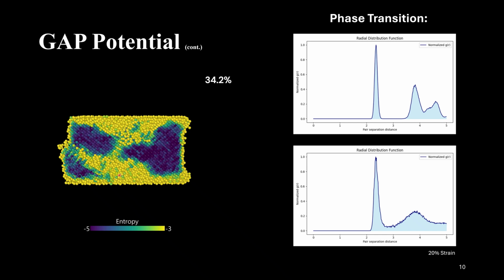And in the experimental paper that I mentioned before and looked deeper into on the next slide, it suggests that the phase transformation for this is a silicon 1 to silicon 2 transformation, which are two ordered transformations. However, looking at the entropy here, we can see that it is indeed not a silicon 1 to silicon 2, rather a silicon 1 to an amorphous phase or a metastable phase. And that's one of the most interesting findings of this project because it goes against what the experimental paper assumed.